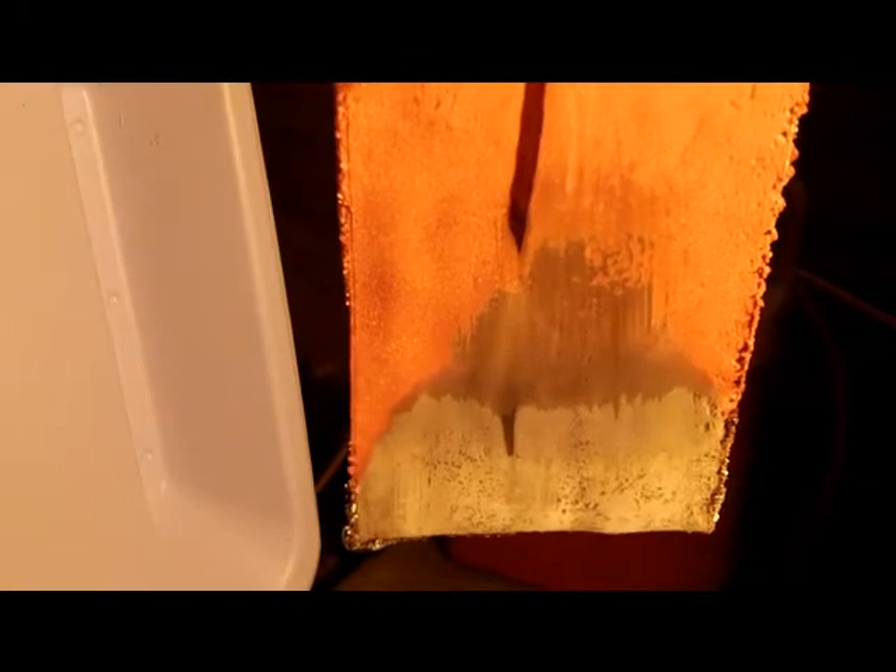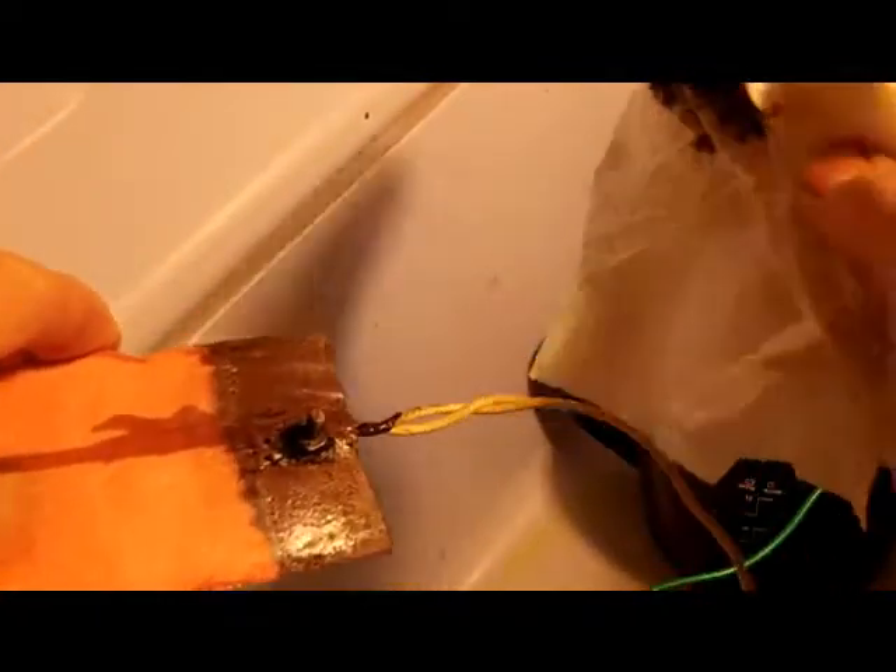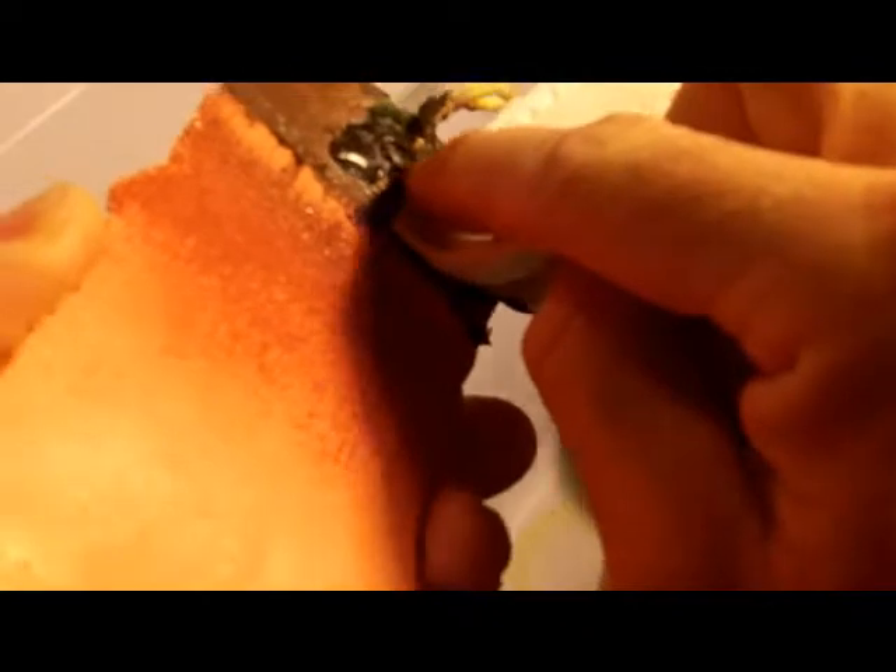It didn't produce a smooth coat on the back side. There's much less copper deposited there — looks like maybe some other metals have deposited on the back side, maybe nickel or something. Having an agitator in the solution may be helpful. It definitely seems to have deposited a different metal near the bottom — could be zinc or tin. That'd be kind of cool to exploit someday.